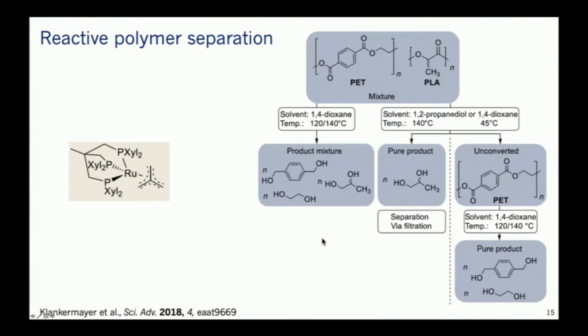This strategy can also be extended to include the separation element, which is very important when you're talking about polymer mixtures. And the solubility of different polymers is used in this case to depolymerize only the ones which are soluble under the reaction conditions. So of course you can choose reaction conditions where everything is soluble and everything depolymerizes, or you can choose reaction conditions where only one of the polymers is soluble. In this case, you get one or the other depolymerized, and you can change the solvent conditions, the reaction conditions, to get the other one back again.